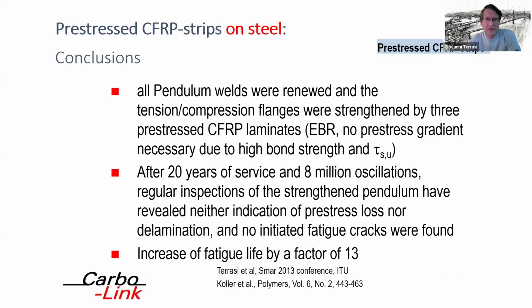So all pendulum welds in this case were renewed, and the tension and compression flanges were strengthened by 3 pre-stressed CFRP sheets, externally bonded and pre-stressed. No pre-stress gradient was necessary here due to the high bond strength of the adhesive and the substrate in this particular case, and due to the fact that we are anchoring far away from the fatigued area.